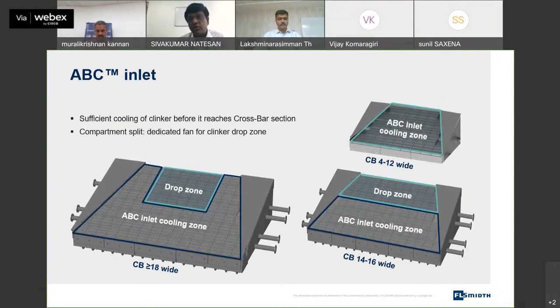Where we see a smaller cooler, where the distribution of clinker is not a problem, we can have the entire cooler designed for a single fan. But when the cooler width becomes wider and wider, we give a separate fan for the drop zone area, where we are sure that clinker is going to fall and maximum cooling is needed. So it doesn't need too much control with MFRs, and a separate fan dedicated to that is going to maximize the heat transfer efficiency, because that is the area where the majority of the clinker is going to fall down.